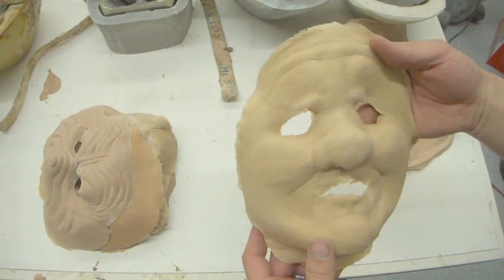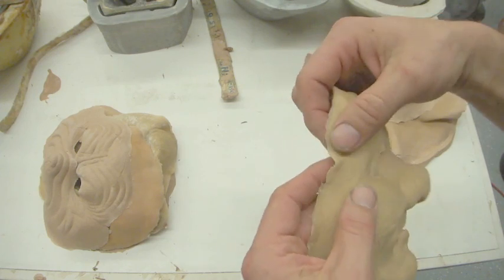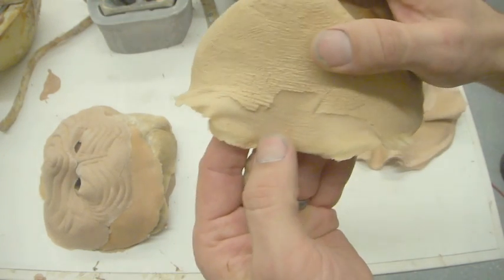Here's another Shrek. You can see that this edge is much nicer. It's got much more of that membrane-like edge on it, so it'll blend in nicely, but it does have quite a bad seam leak on the bottom, and then more seam leaking in the back.